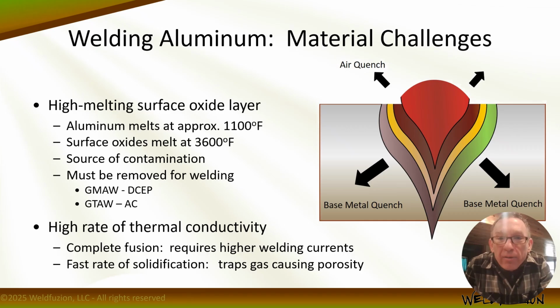Aluminum, on the other hand, forms a protective oxide layer that's invisible. We can't see it. It forms to a maximum thickness over the surface area, and it won't completely consume the parent aluminum material, at least for a really long time. However, you can't see it, so it's difficult to tell how much oxide layer has formed and how thick it actually is.